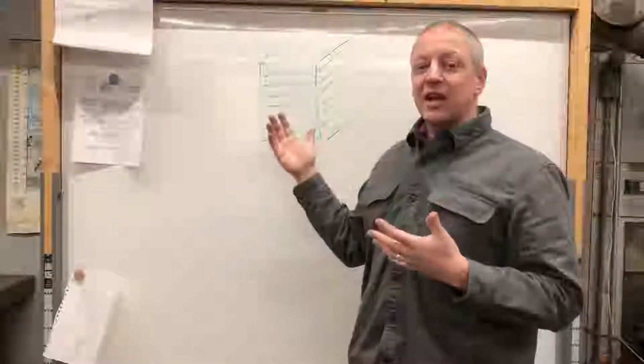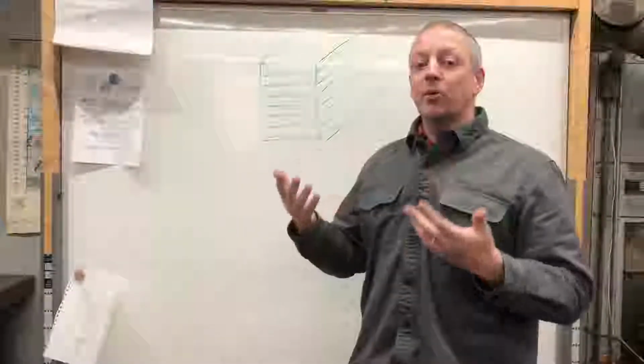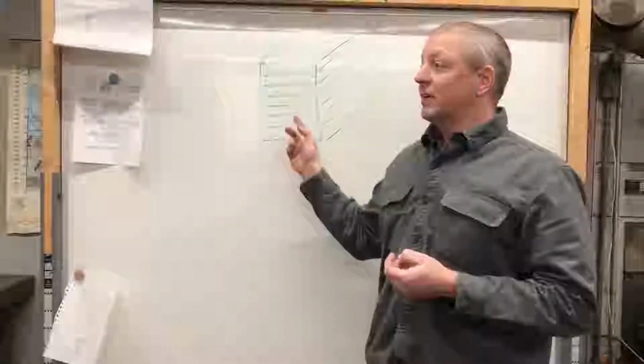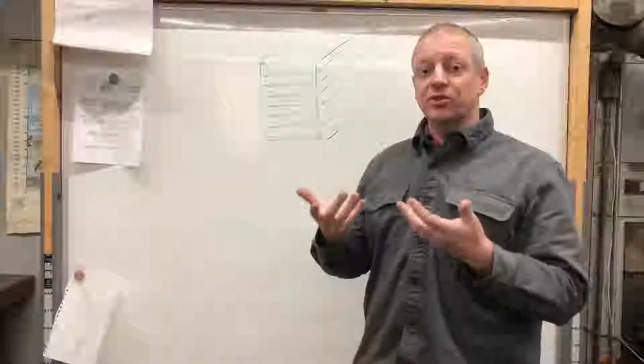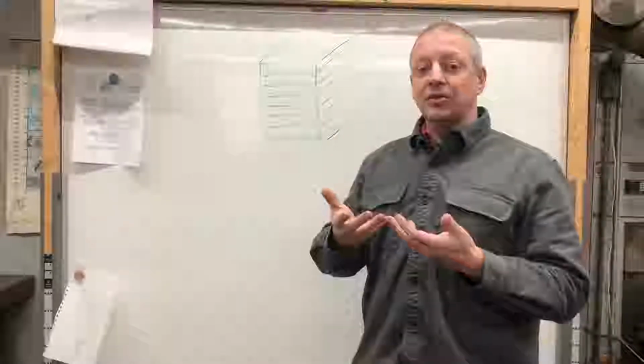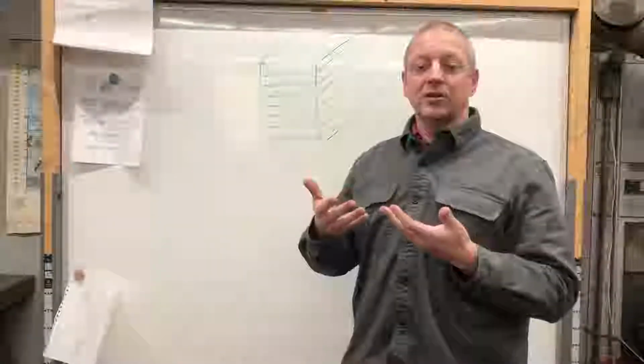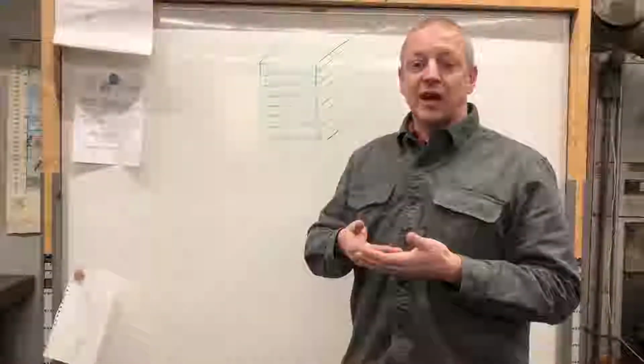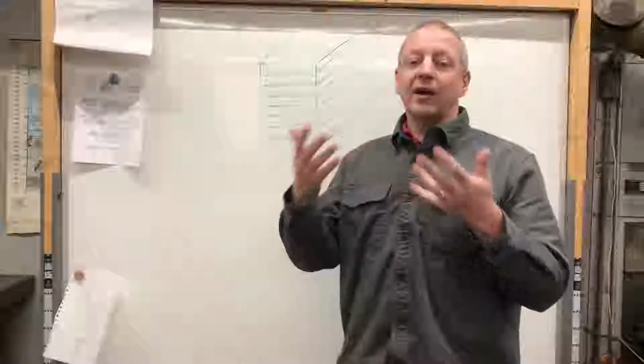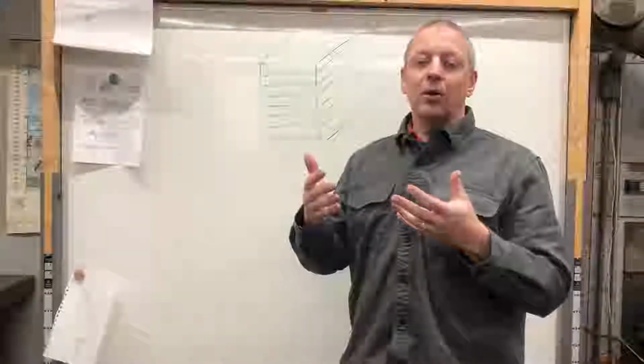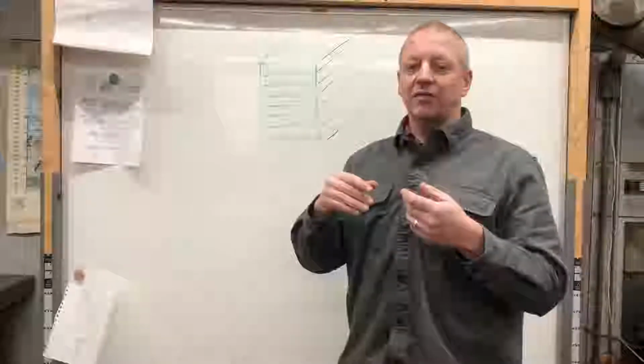As that carbon becomes more mobile, it is also available to come to the surface and react with the oxides on the surface, and break those oxides down. So you've got iron oxide, we'll just say it's FeO. There's a bunch of them, but we'll just call it FeO in this case.